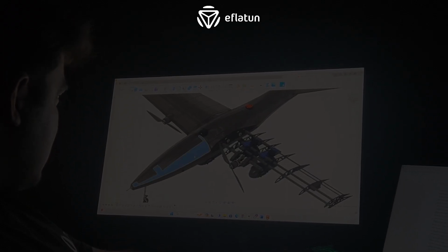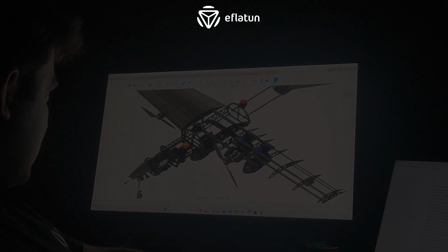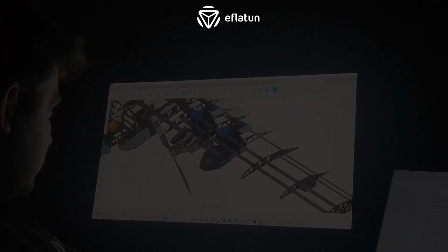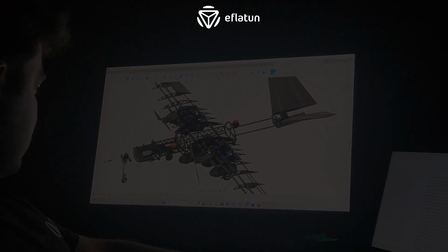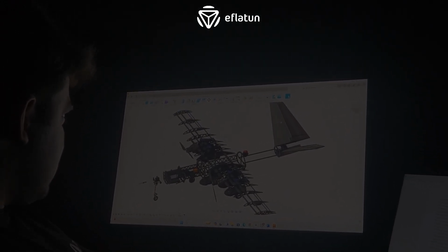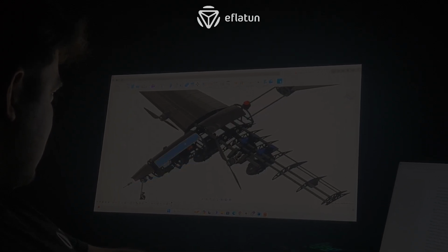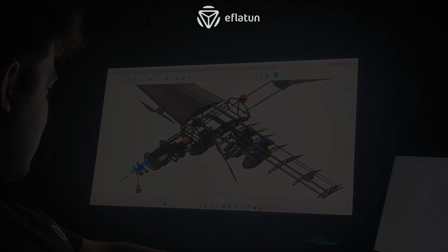After these stages, detailed aircraft design began, emphasizing lightweight construction using composite materials. Carbon tubes and ribs from carbon fiber sheets were used for the wing and tail frames, while wooden plates instead of carbon fiber were chosen for the fuselage frame due to electrical conductivity concerns. Sandwich panels comprising PVC foam between layers of carbon fiber were preferred for the outer surfaces of the fuselage, wings, and tail due to their lightweight and rigid structures.